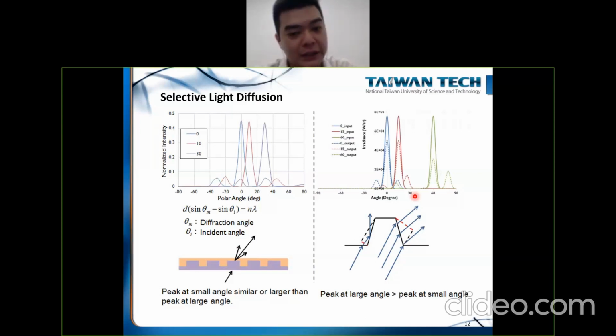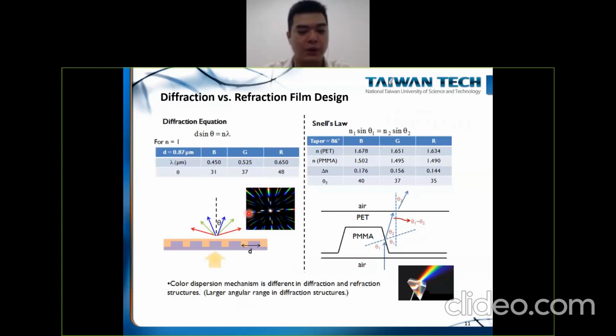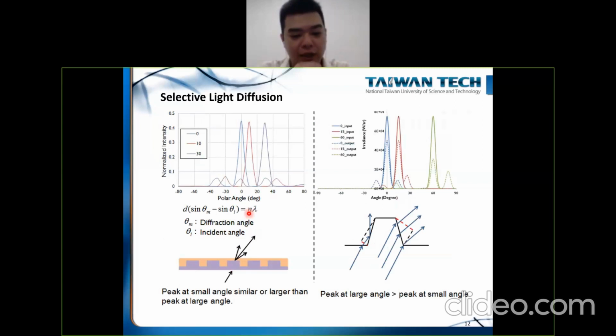Okay, and in the last slide we talked about the normal angle image light entering the film. And what if the light enters the film from a larger angle? What we can see is that we need to revise this equation to something like this. And if we do some simulation, we can see the blue line here, red line here, and the purple line here show the light entering from the 0 degree, 10 degree, and 30 degree respectively. And after entering this diffraction structure, it will be diffracted to certain angle.